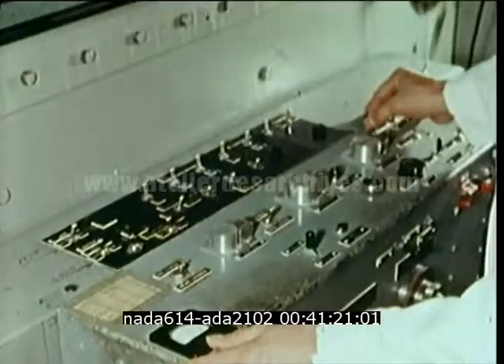Approximately 92% of the fuel originally within the core was recovered from inside the reactor vessel. The remainder escaped from the vessel at the time of the accident. Fission product release was about 5%, which is not in complete agreement with the observed loss of fuel. Debris from the bottom of the vessel was sifted according to mesh size. Laboratory analysis revealed the major constituents to be uranium, aluminum, boron, iron, and indissoluble oxides.